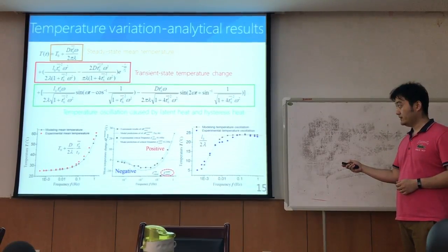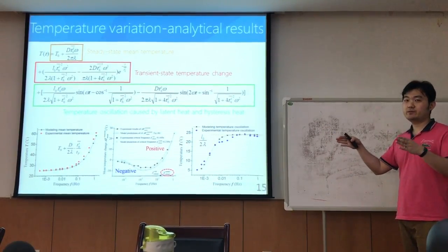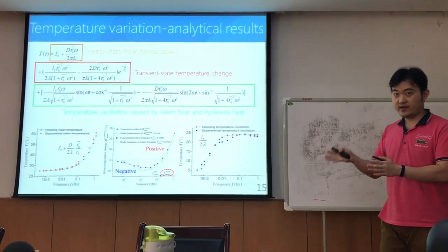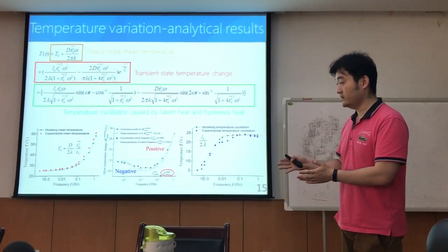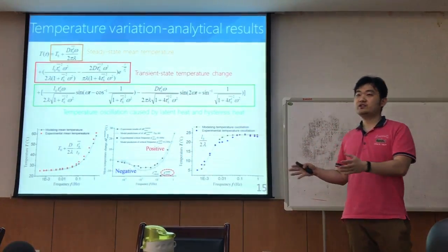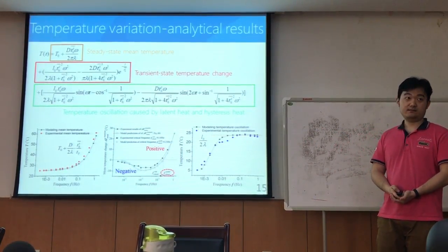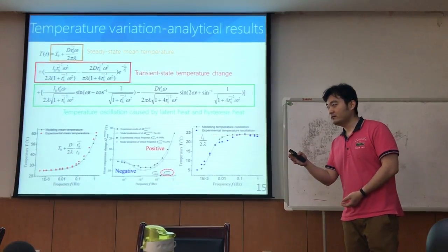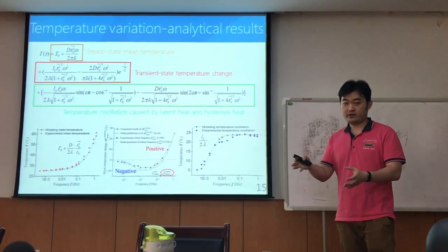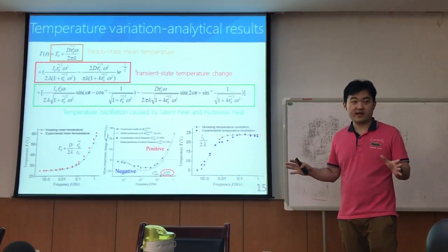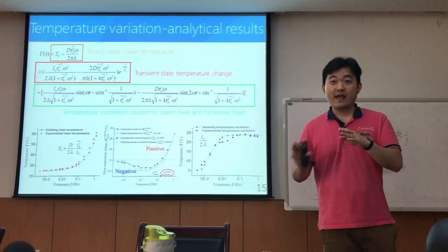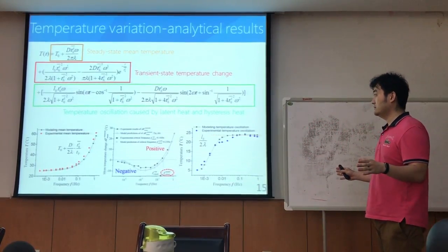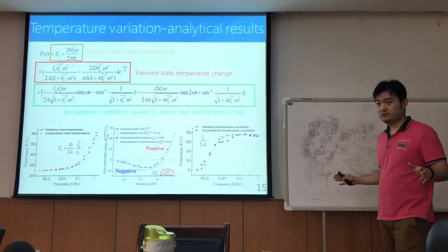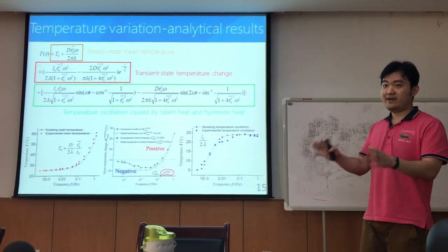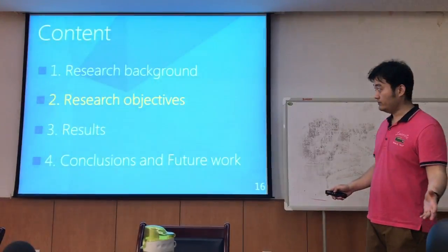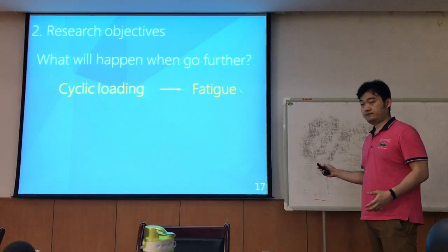Okay. So with this temperature variation prediction, we can predict the stress level during cyclic loading condition. And this is very important for engineering applications. But for engineering application, this prediction may work for 300 cycles, 500 cycles. Okay. How about 5,000 cycles? Or 50,000 cycles? Or 10 million cycles? As we all know, material will go to fatigue.